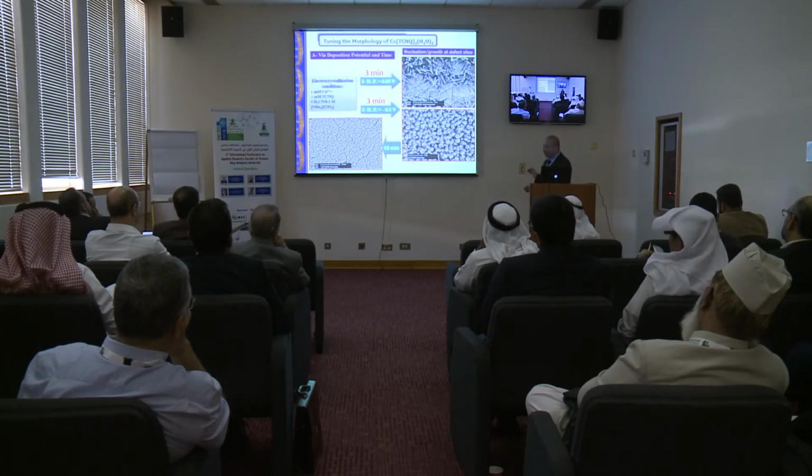So if you have a simple experiment, 1 millimolar cobalt and 2 millimolar TCNQ in the presence of acetonitrile with this supporting electrolyte, you're applying at that deposition potential, then you can form these kind of needle-shaped microstructures of the cobalt TCNQ. And the real time of this is around 3 minutes. So you can make this material in a 3-minute time.